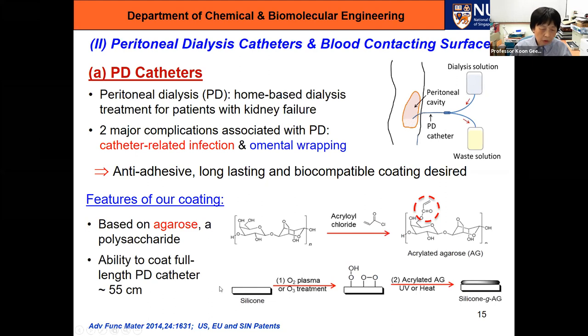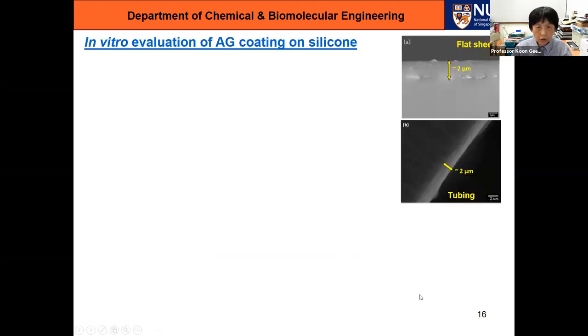Then we introduce reactive groups on the surface of silicone by using either oxygen plasma or ozone. And then using these surface reactive groups, we graft the acrylated agarose onto them using either heat or UV. So this shows the coating.